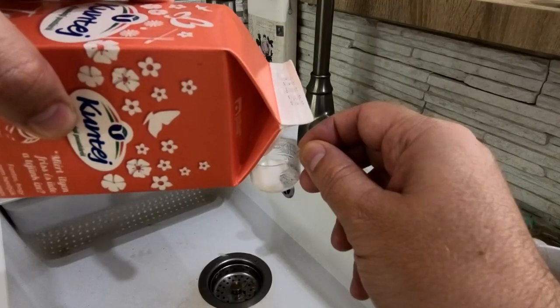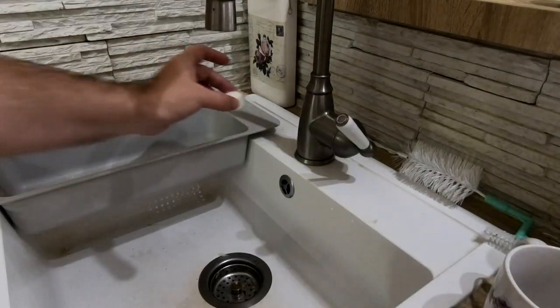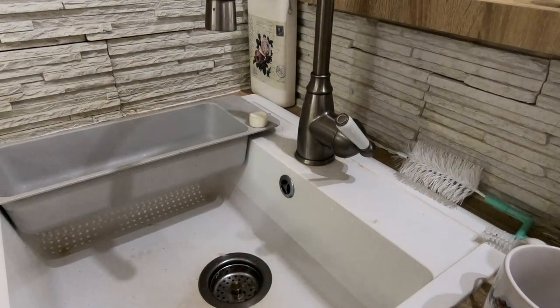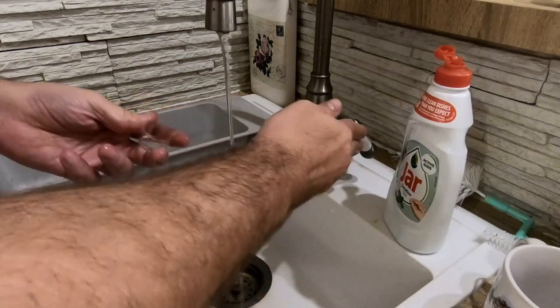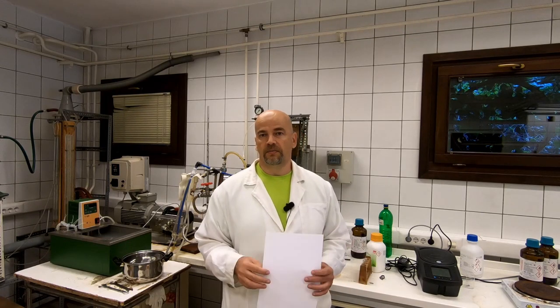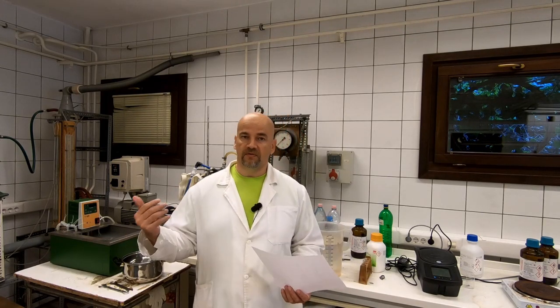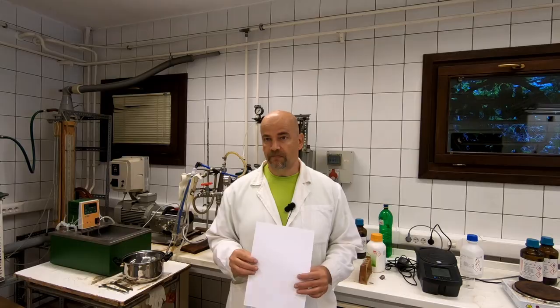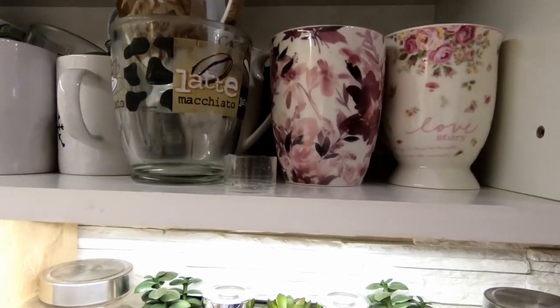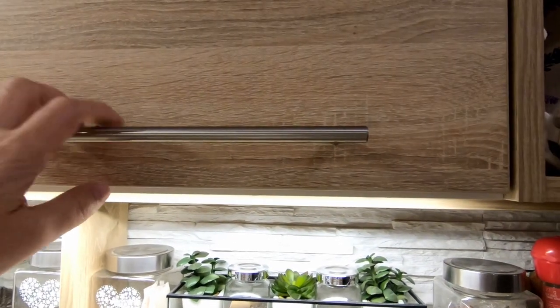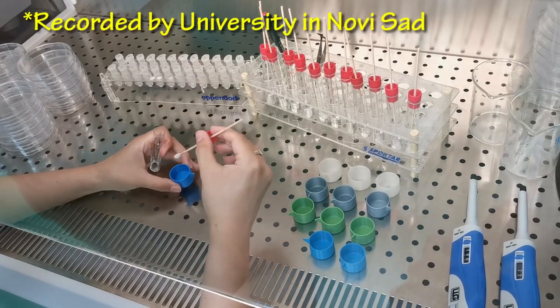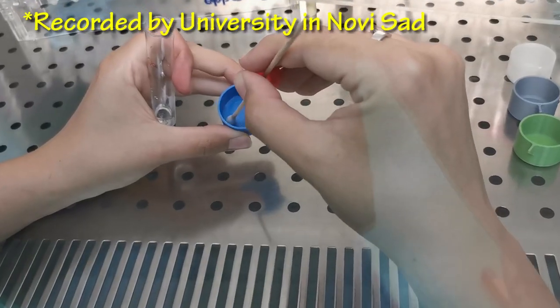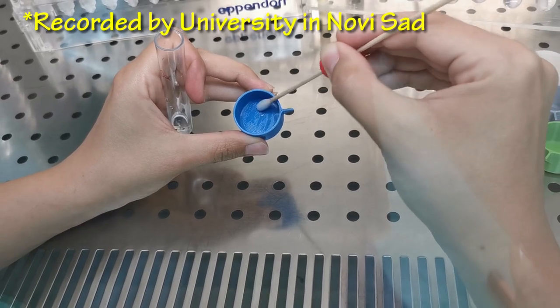And they simulated use in a kitchen with milk. For example, they placed milk in the cup, left it there maybe 15 or 20 minutes, and then washed the cup only under the tap using dish soap, not in the dishwashing machine, because it cannot handle high temperatures. Then they left it there and repeated the procedure the next day. And after 10 days, they checked the bacteria colonies on the surface.